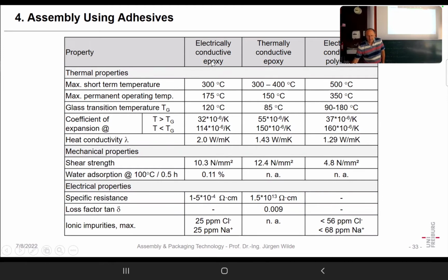In these electrically conductive epoxies, we have a heat conductivity which is given as 2, or here 1.5, or also 1.5. That is for traditional adhesives, which are used, for instance, in thick film technology. Companies have made quite an effort to go to higher values, and we also did some research. Some of my PhD assistants worked in that field of adhesive bonding for high power, but there was great progress on the adhesives, and industry developed adhesives where they claimed up to 20.